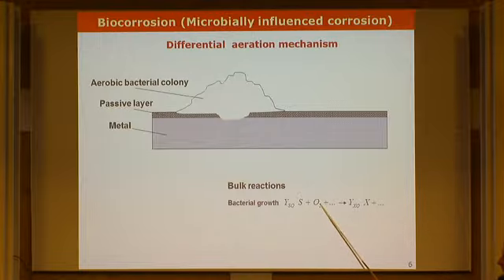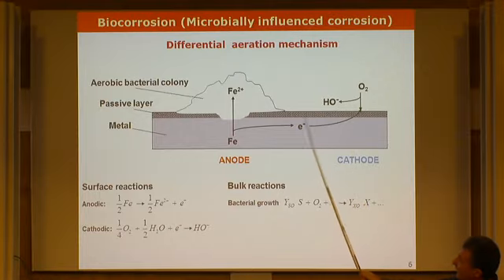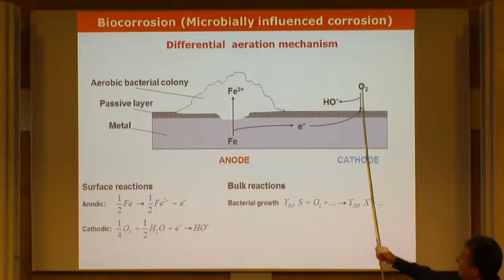You should have some anodic process, which is the metal oxidation and release of ions in the solution. You should have some cathodic space on this metal where oxygen is reduced to hydroxyl. So these electrons now go to the metal and will provide here oxygen reduction. On the other hand, you have some bulk reactions like ferrous ion oxidation, quite quick in water, and then precipitation because you may create an alkaline environment in this case. So you have rust as well.